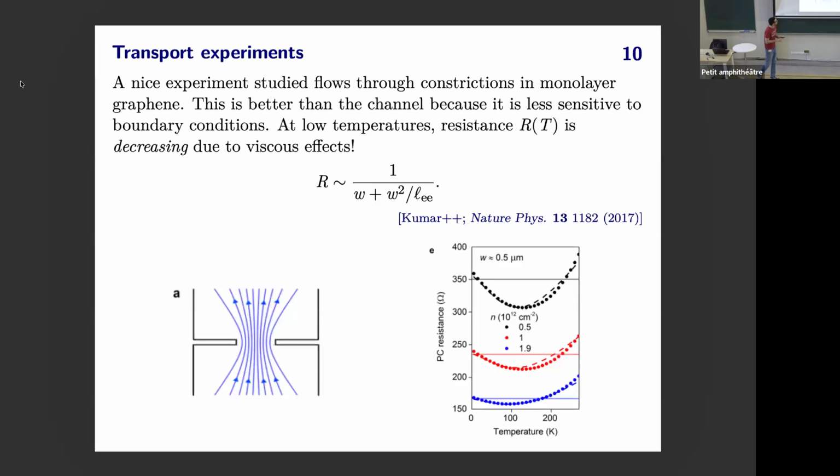In practice, the hydrodynamic regime is often limited to some temperature range, because if you heat the system up enough, then the temperature dependence in L_MR makes it very small, and this hierarchy of length scales that I described is not reachable. So in these graphene-based devices, usually this means you're at about 100 Kelvin or below, where the momentum relaxing length scale can be 10 times the momentum conserving one.